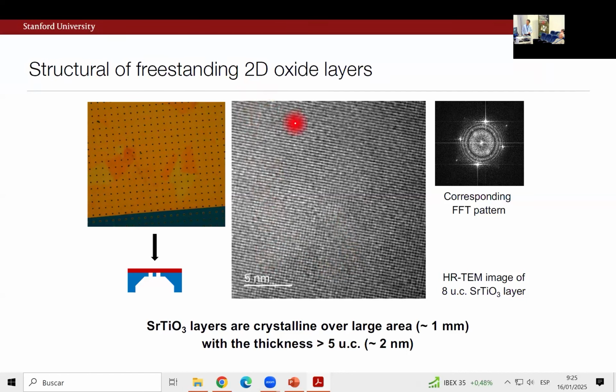We weren't using a very fancy microscope at the time, but in any case, you could see basically a lattice, right? And the summary statement would be that if we have 8-unit cells, or actually specifically 5-unit cells or larger, this system looks essentially single crystalline over very large areas, the field of view.